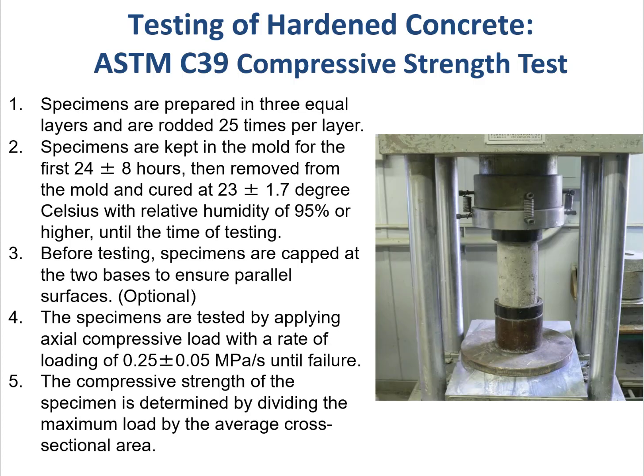So let's talk about the testing procedure. First, the specimens are prepared in 3 equal layers, and each layer is rodded 25 times. The specimens are then kept in the mold for the first day, then removed from the mold and cured at approximately 23 degrees Celsius with a relative humidity of about 95% or higher until the time of testing. Before testing, the specimens can be capped at the 2 bases to ensure parallel surfaces.